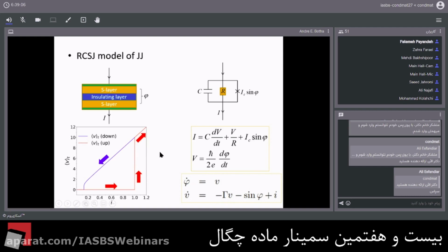The junction then can be seen to exhibit a type of hysteresis loop. That is, if you start increasing the bias current from zero, increasing the current upwards, at first there is ideal superconductivity. In other words, the current increases without any increase in voltage across the junction. That is until you reach this critical current, which in these units has been normalized to 1. At the critical current, the junction then jumps to a resistive state.